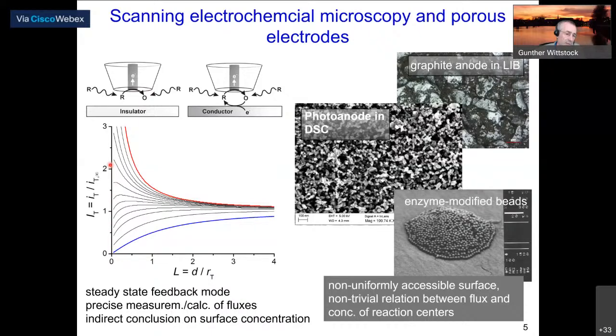And as a quantitative result, you see that plotted here in the blue curve. In this diagram, this shows the normalized current versus the normalized distance. The current is usually normalized to the current which we record far away from any surface. Therefore, it's called i_T,infinity, for tip at infinite distance. And that is a typical microelectrode current.